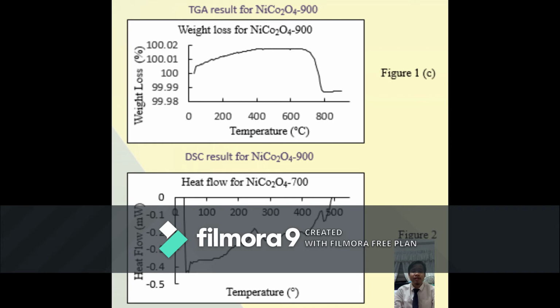The increasing weight of the catalyst sample in the TGA analysis may be because of the existence of contaminants and impurities, such as oxygen in the dry nitrogen purge gas, that lead to the absorption of oxygen. Another significant factor which influences the true sample temperature and weight is the effect of radiation on the sample. At above 500 degrees C, radiation becomes the dominant mechanism for heat transfer, particularly when using an open cup sample pan. As an example, under the same conditions, a black sample can be at a higher temperature than a white sample.